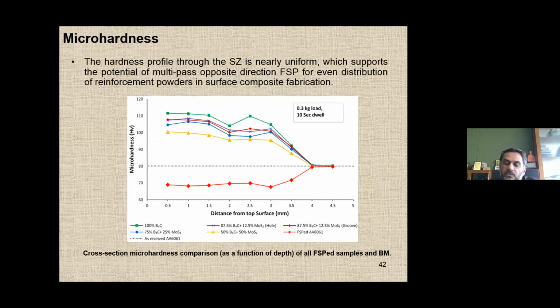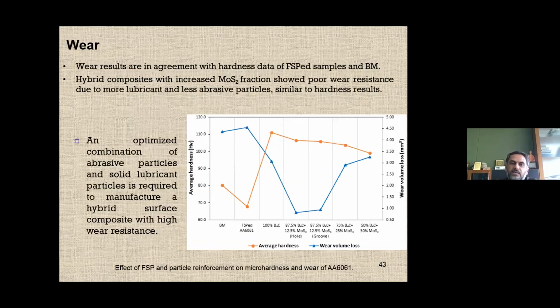And this trend is also longitudinal, and vertical also. You see here that hardness measurements were carried out not only in the transverse direction, but within the stir region also, from top to the bottom. So this also indicates that once you have the highest percentage of MoS2, you get the least hardness, and the green one is the indication of 100% B4C. And those trends are also matching with the wear behavior.